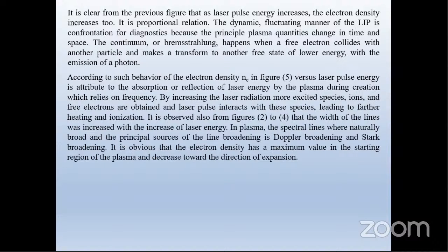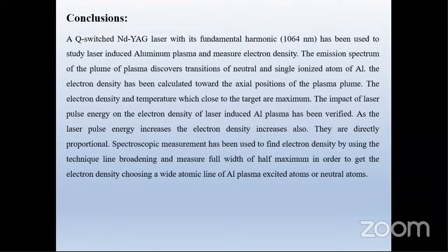By increasing the laser radiation, more excited species, ions, and free electrons are obtained, and the laser pulse interacts with these species, leading to further heating and ionization. It's observed also from figures 2 to 4 that the width of the lines increased with the increasing of laser energy. In the plasma, the spectral lines were naturally broad, and the principal sources of the line broadening are Doppler broadening and Stark broadening. It's obvious that the electron density has a maximum value in the starting region of the plasma and decreases toward the direction of expansion. Finally, a conclusion: